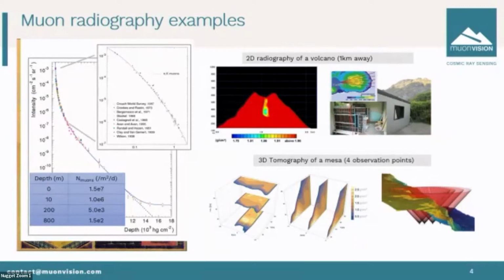At the surface, we all know there's about one muon per square centimeter per minute. At 10 meters in rock you still have a million. But the moment you start going deeper, that number drops. And if the number disappears, that means your measurement will take longer and longer. Your radiography measurement is essentially like taking a picture with a very long shutter time. With a conventional picture, the shutter time is milliseconds. Here we have to wait days to weeks, depending on the depth at which we are.